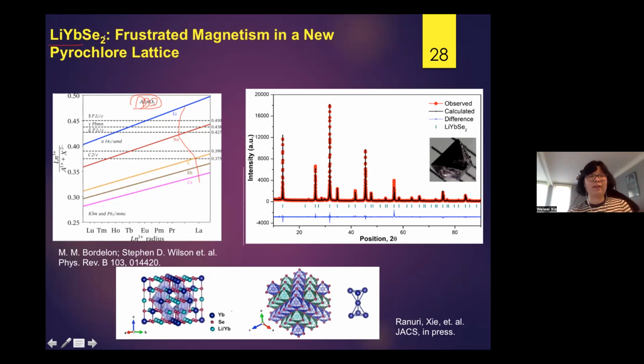For me, I feel not surprised. We find that it's in a cubic structure type. It's a new pyrochlore lattice. So this is the crystal structure, and this is the crystal we grow. We can grow very big crystals, and we find that ytterbium is in this lattice. It's very interesting. So now we made it.